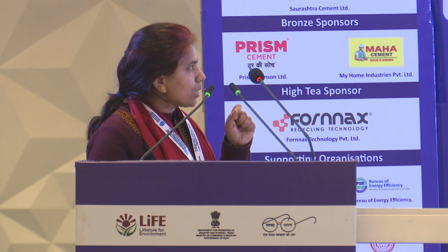That is the basic challenge, which can be understood or regulated by understanding this early age hydration chemistry, which is very complicated but very important to address because it has multiple steps, and these steps have different chemistry. So we need to understand how the chemistry is changing during this time period. And the second is the microstructural modification occurring at this stage. The product, calcium silicate hydrate, is basically known as the DNA of concrete. No one knows the stoichiometry of this C-S-H, and if we can identify the stoichiometry of this C-S-H and what type of C-S-H is forming at this time, we can